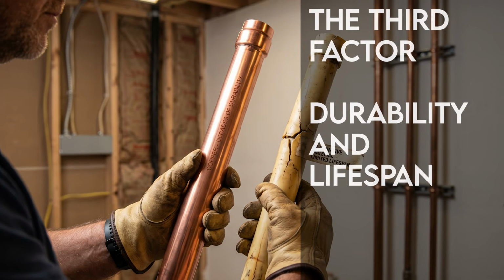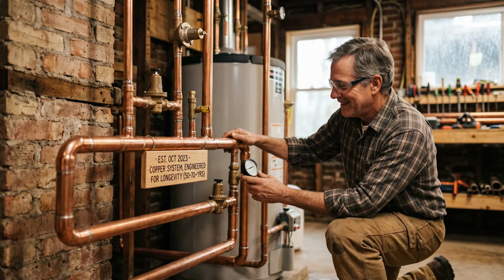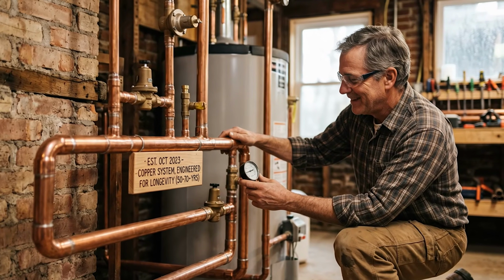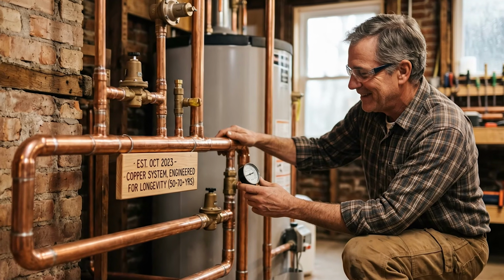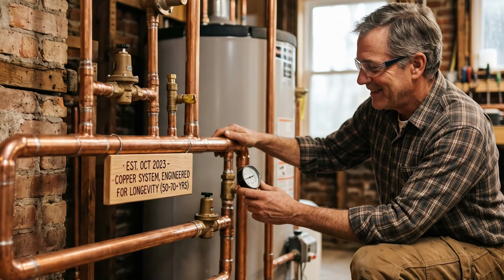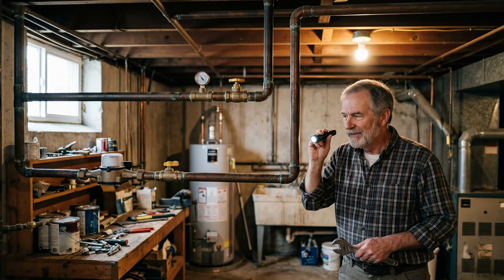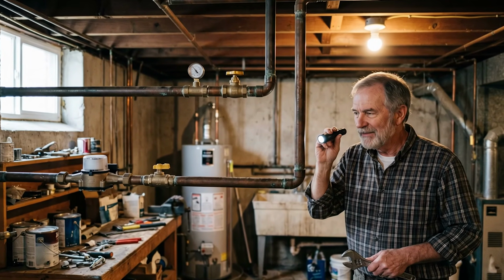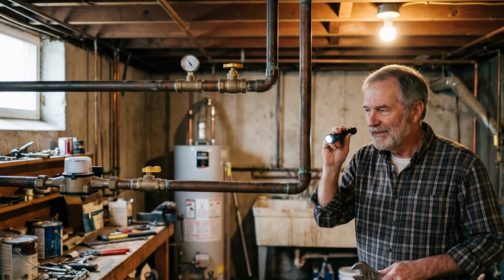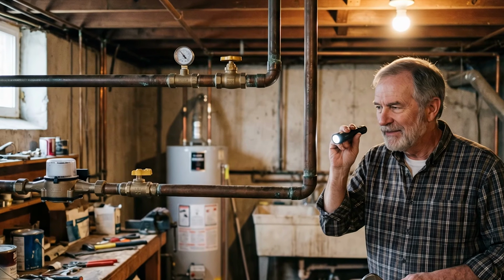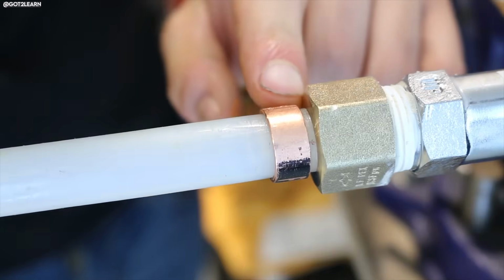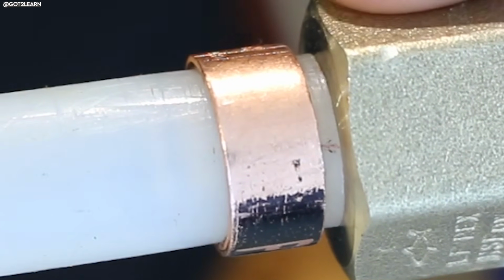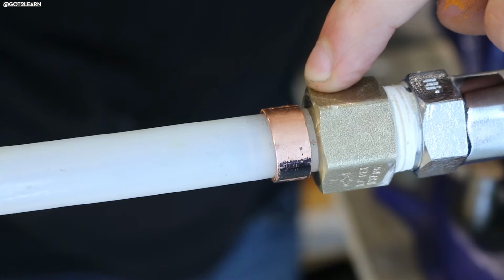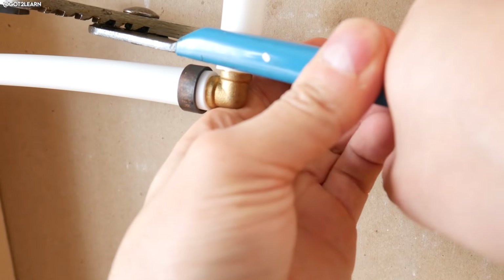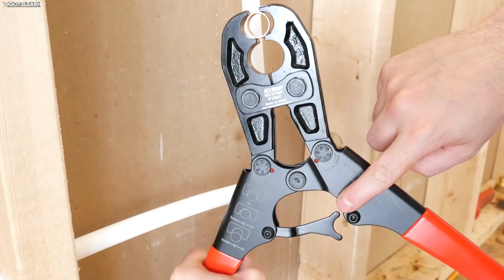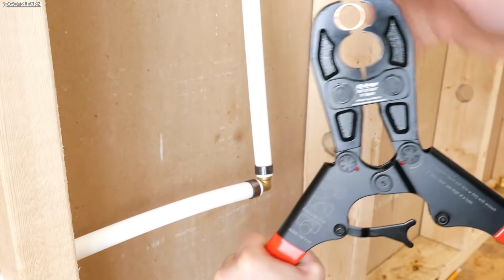The third factor to compare is durability and lifespan, and this is where copper has been king for decades. A properly installed copper system can last 50 to 70 years or more. There are homes with copper pipes from the 1950s still going strong. That said, copper is not bulletproof. Acidic water with a low pH can cause pinhole leaks over time, especially in certain regions. If your water is aggressive, copper may corrode from the inside out, and you will not know it until you see a stain on your ceiling.